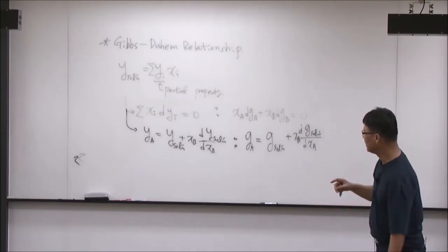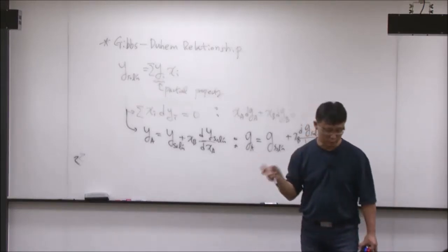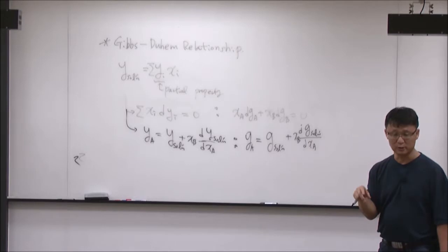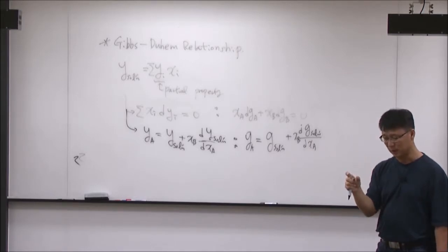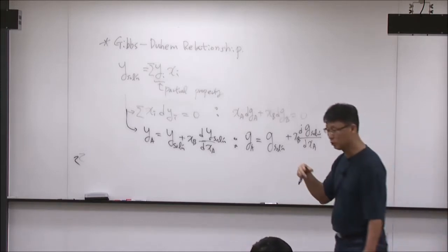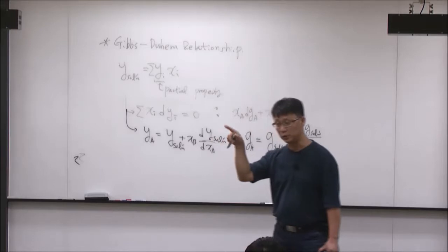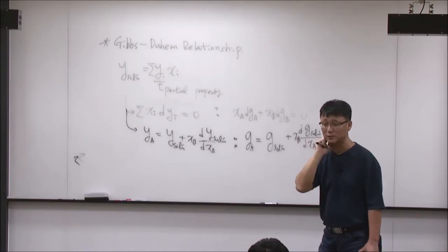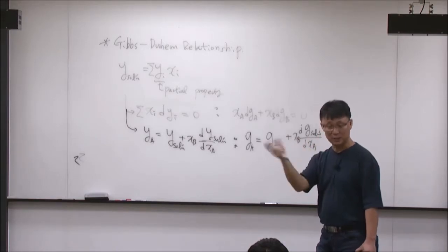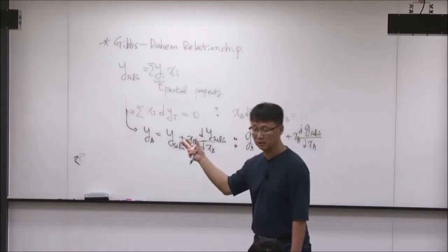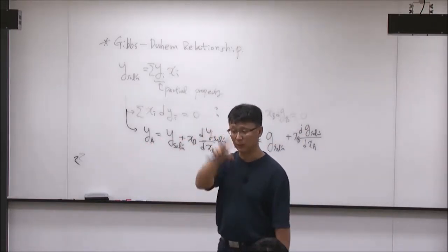The other example is, we can also develop technology to measure the Gibbs energy directly. One of those methods uses electrical current. Well, theoretically it's voltage, because in electrochemistry, Gibbs energy can be converted to electrical energy, especially voltage. I don't know whether you have learned corrosion or electrochemistry already. Gibbs energy is minus nFE, where F is the Faraday constant and E is the electrical voltage. So Gibbs energy can be converted to the voltage.